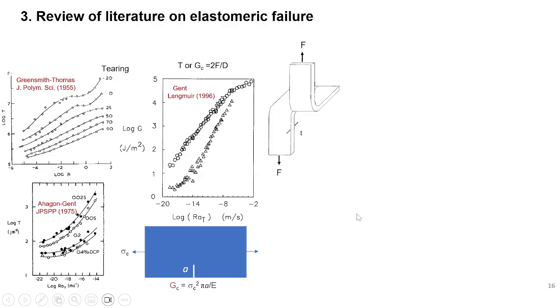So let me now quickly, with that background, I know it's still rather abstract, jump to the third topic of reviewing the literature. The literature is very rich, 70 years of continuous research, since the 50s. What you typically do is the tearing experiment. What was found was that if you tear faster, there's more force arising from the faster tear. So that's one of these lines.